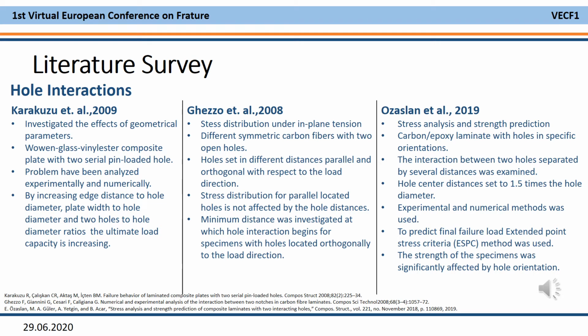Karakuzu et al. analyzed a woven glass vinylester composite plate with two pin-loaded holes. The aim of this study was to investigate the effects of geometrical parameters such as edge distance to hole diameter, plate width to hole diameter, and the distance between two holes to hole diameter ratios on failure loads and failure modes. Problems have been analyzed experimentally and numerically. By increasing all three ratios, the ultimate load capacity increases.